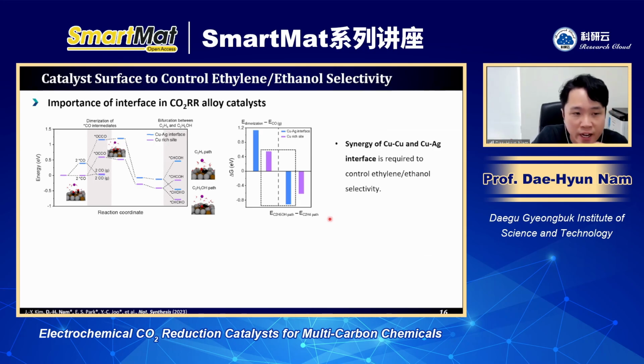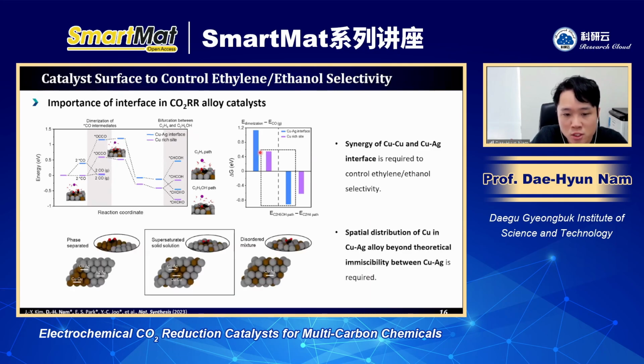To study this idea, first we did some calculation to compare the activation energy for controlling the ethylene and ethanol pathway in terms of the copper-rich site and the copper-silver interface. When you compare these, the major conclusion is that because we need both a copper-rich site and a copper-silver interface, we need this kind of supersaturated solid solution. It means there should be copper-silver and copper-copper sites together.